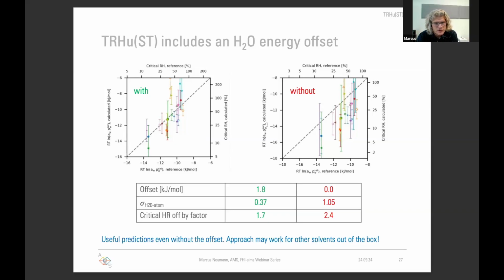If you don't have the offset, then we still get phase transitions right to within a factor of 2.4, which is actually not much worse, but it's a little bit worse. So when we do pharma work, we use the offset.